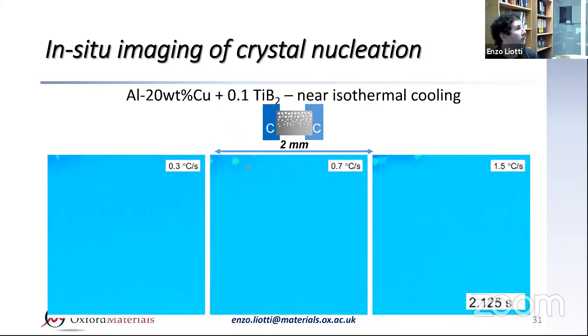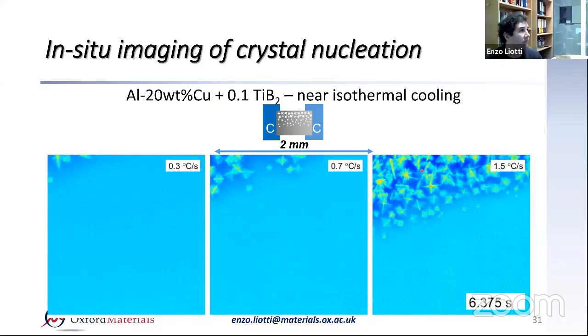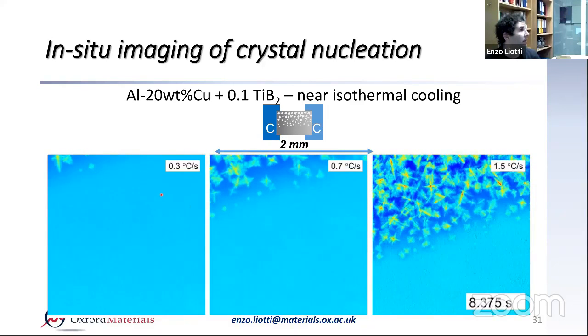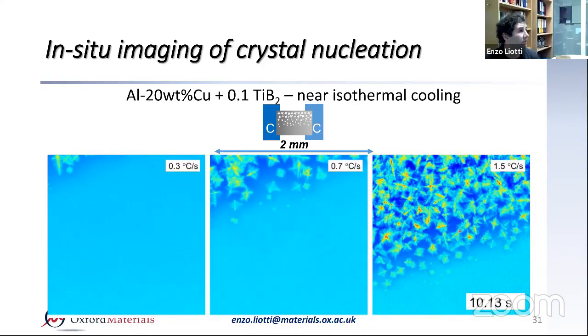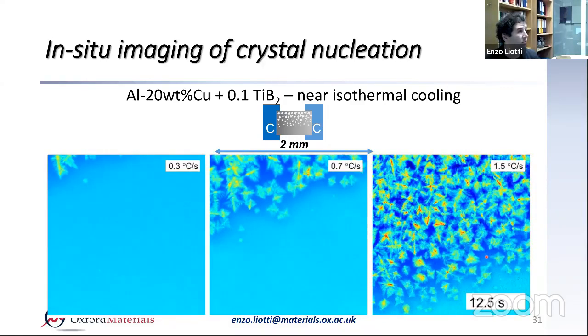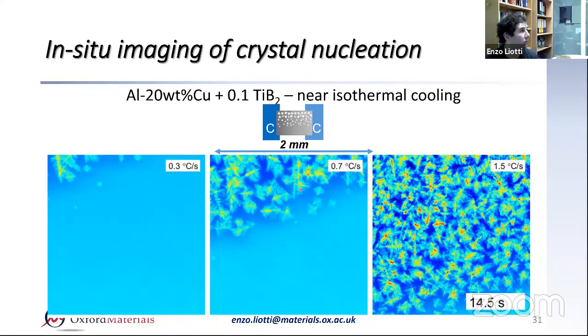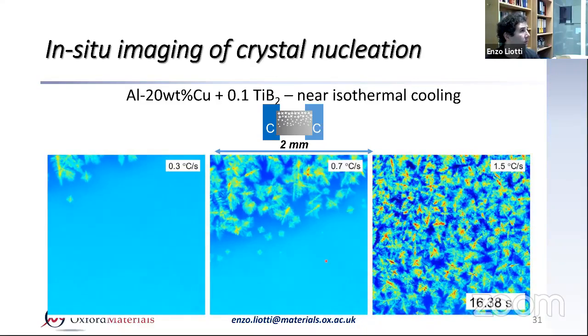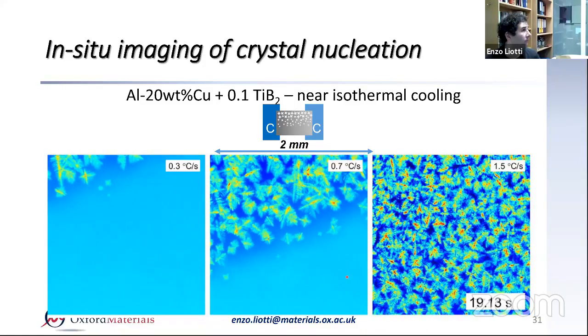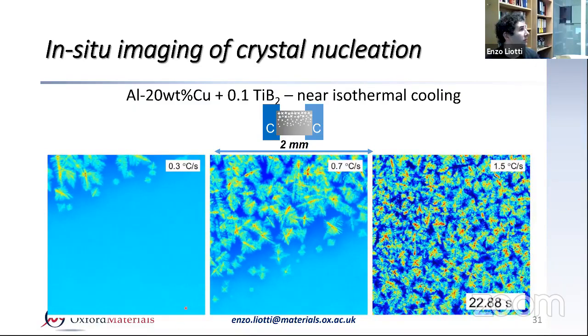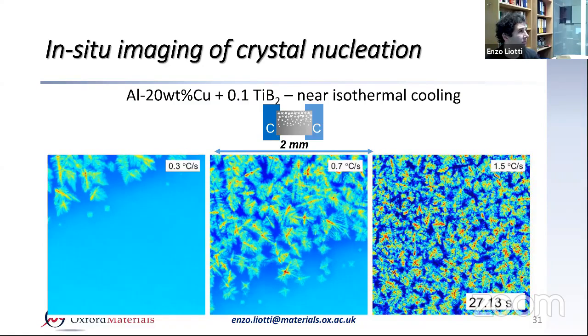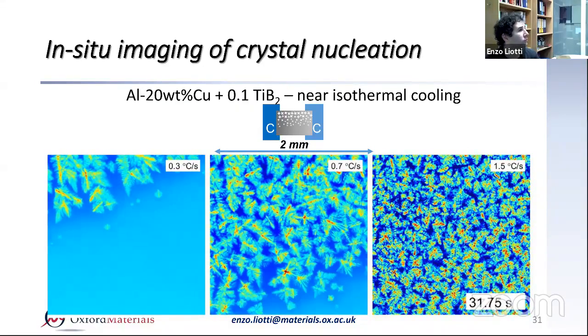So you can see that the grains form, and the one on the right is faster, so they appear in the field of view much faster. Qualitatively, you can also see the solute segregation in the mushy zone, the darker blue compared to the bulk liquid. But one thing that is immediately visible is that, despite the fact that it takes less time on the right side to solidify, just because of the cooling rate, you can see that the nucleation was more copious.